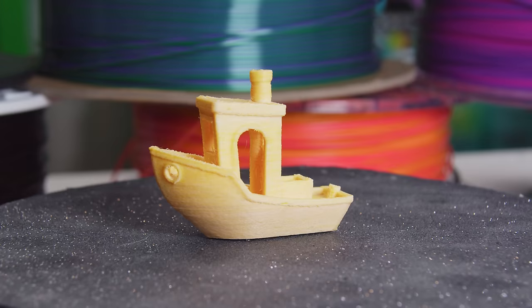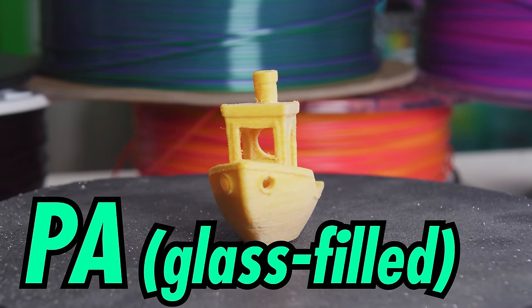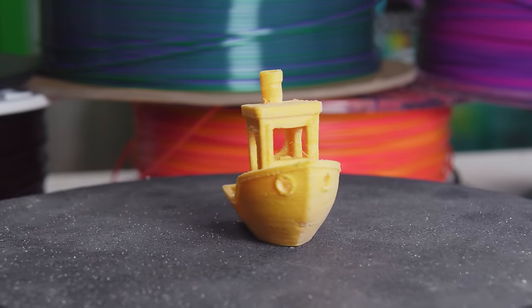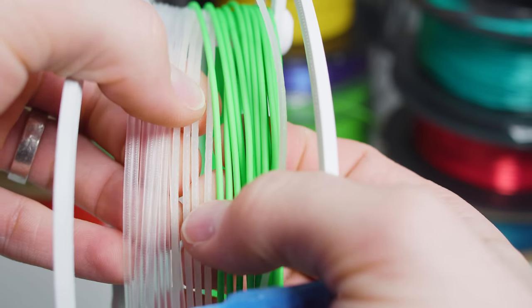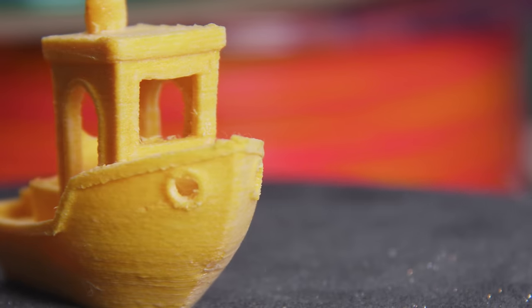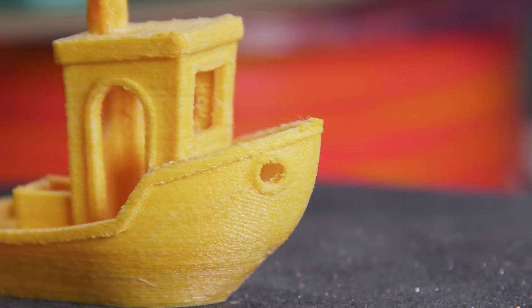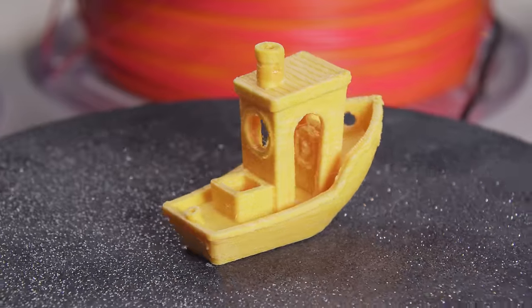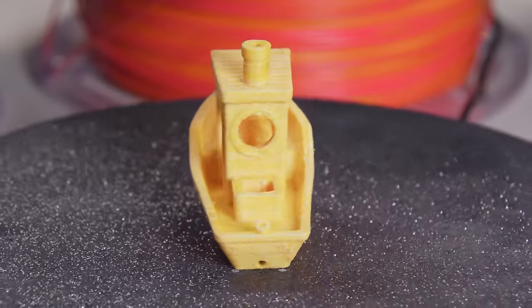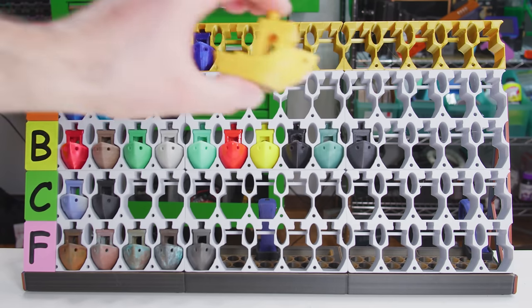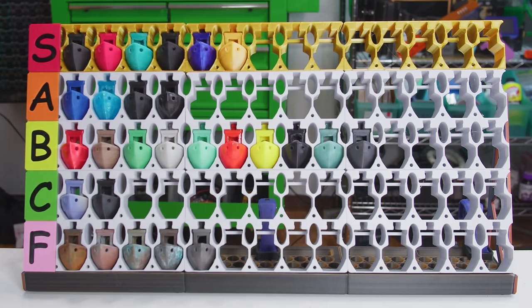That said, if you want a seriously strong, far-friendlier filament, especially if you have an expense account, you want GFPA. Glass-filled nylon is one of the modern world's most important materials. From chainsaws to handguns, a huge variety of heavy-duty gizmos are made practical and inexpensive by injection molding this exact same material. Compared to pure nylon, GFPA is massively stiffer, tougher, and more resistant to heat, abrasion, and impact. The glass fibers reinforce nylon strength, and they cut warping to the point that this is actually a fairly easy filament to print. Glass fibers are extremely abrasive, and they drive up the print temperature. You really want a tungsten carbide or gemstone tip, plus abrasion-resistant drive gears. But, with the right settings, GFPA is a pleasure to print while being so durable, it's a viable alternative to machined aluminum. I'm gonna put glass-filled nylon in S tier. This is high-end stuff that calls for a high-end printer, but if you need this level of high-end performance, you can probably afford it.